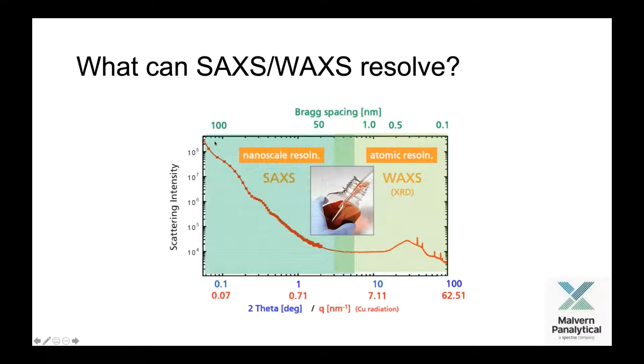Generally, if you're doing SAXS you'll be looking at structures on the order of 100 down to about 1 nanometer, and WAXS can go even lower to about 0.1 nanometers. They cover different ranges of 2θ and Q — the scattering vector in inverse nanometers. Essentially, the size of the things you're looking for will help determine whether you want to run SAXS or WAXS.